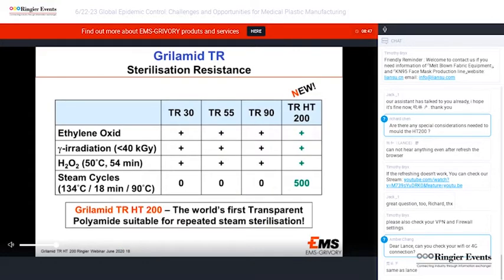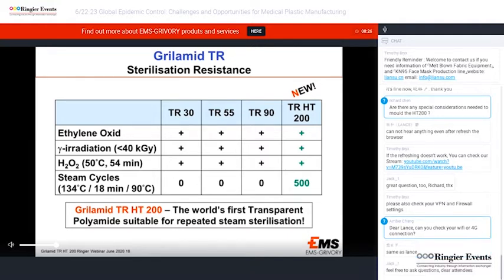On this slide, we can see that all Grilamid TR grades have a good resistance against the common sterilization methods such as ethylene oxide, gamma irradiation under 40 kGy, and hydrogen peroxide at 50 degrees Celsius for 54 minutes. However, where Grilamid TR and other transparent polyamides have fallen over in the past is repeated steam sterilization at 134 degrees, a common sterilization method in the medical and healthcare sector.